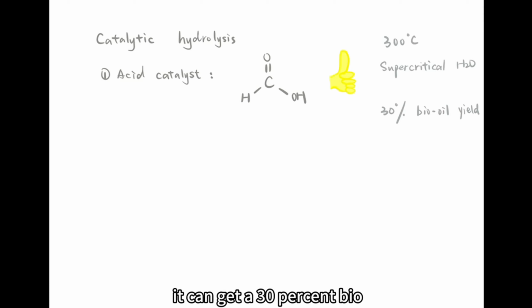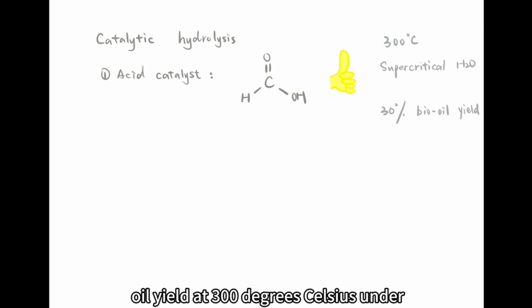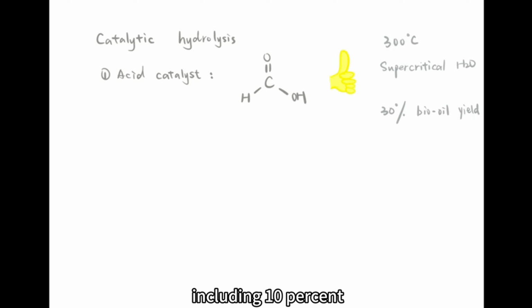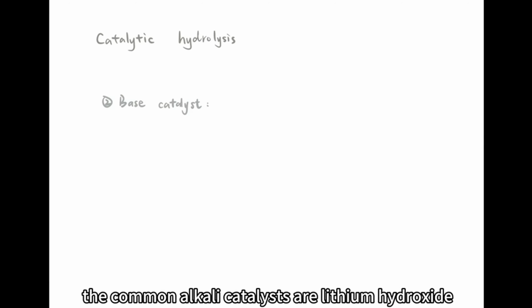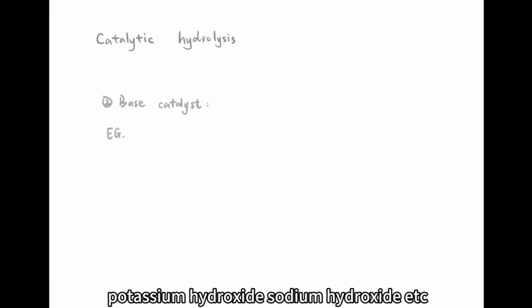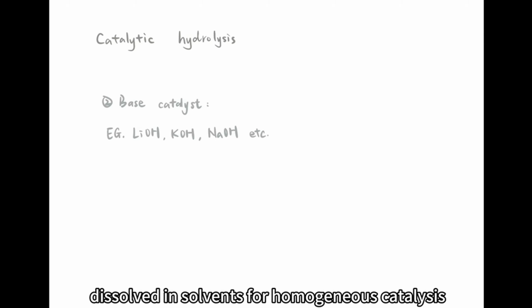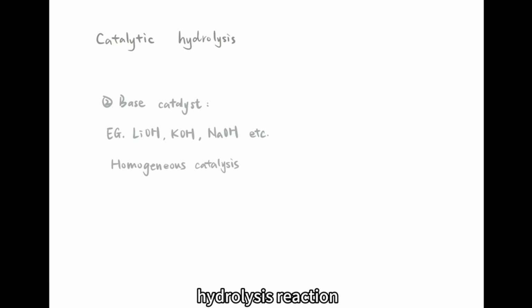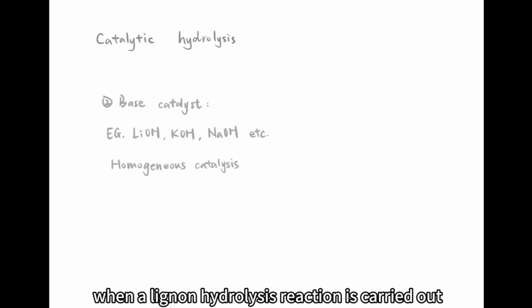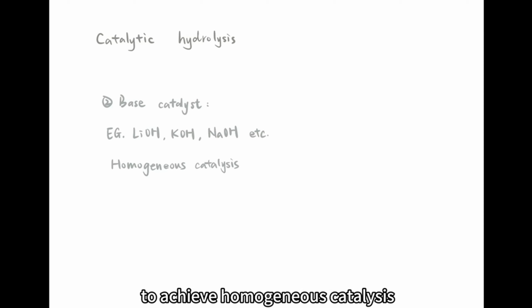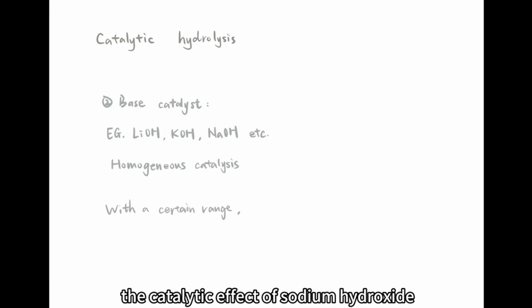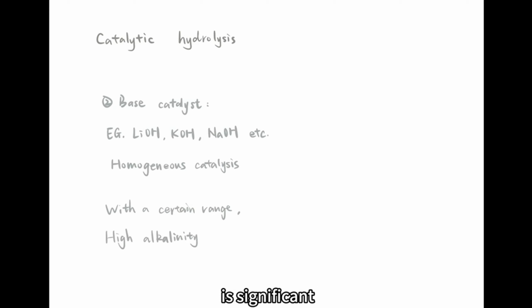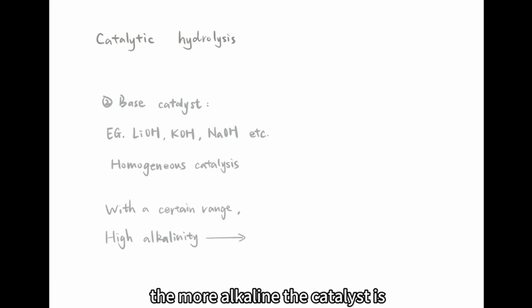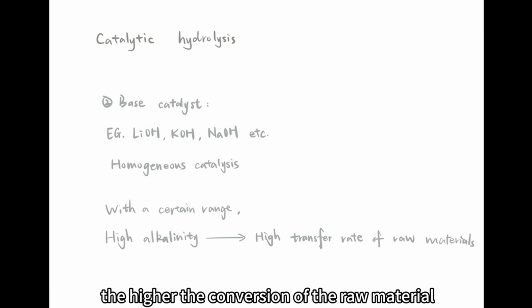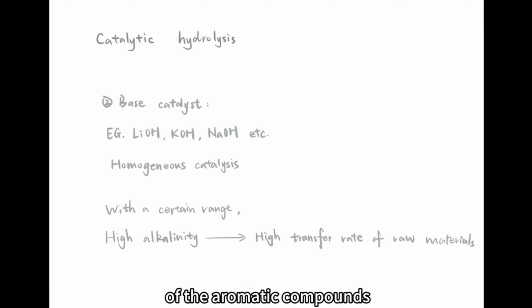It can be used to obtain a 30% biooil yield at 300 degrees Celsius under supercritical water conditions, which contains 10%-12% of monophenolic compounds. The common alkali catalysts are lithium hydroxide, potassium hydroxide, sodium hydroxide, etc. When a lignin hydrolysis reaction is carried out, they are generally dissolved in the solvent to achieve homogeneous catalysis. The catalytic effect of sodium hydroxide on the hydrolysis of lignin is significant. Within a certain range, the more alkaline the catalyst is, the higher the conversion of the raw material and the higher the selectivity of the aromatic compounds.